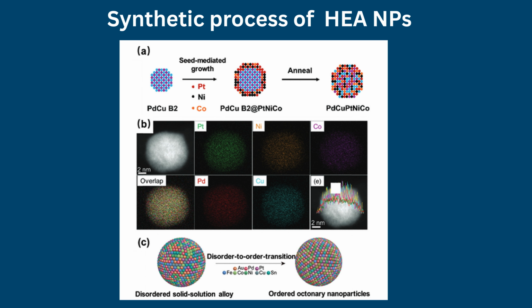A related seed-mediated strategy has also been developed using platinum, palladium, and gold nanoparticle seeds for HEA-MMNP synthesis. In one representative example, platinum seeds were reacted with cobalt, nickel, copper, and zinc precursors in oleylamine at 350 degrees Celsius, yielding highly uniform PtCoNiCuZn MMNPs, approximately 5 to 6 nanometers in diameter. Oleylamine simultaneously served as solvent, surfactant, and reducing agent, facilitating controlled heterogeneous nucleation and alloying while suppressing galvanic replacement reactions.